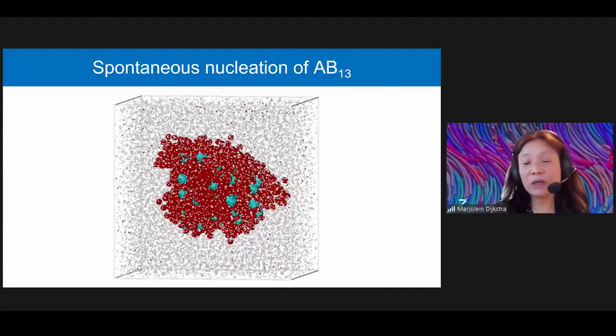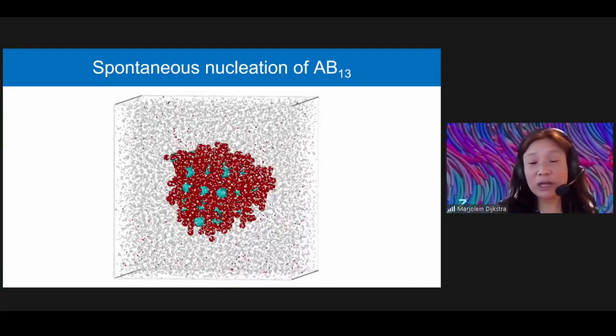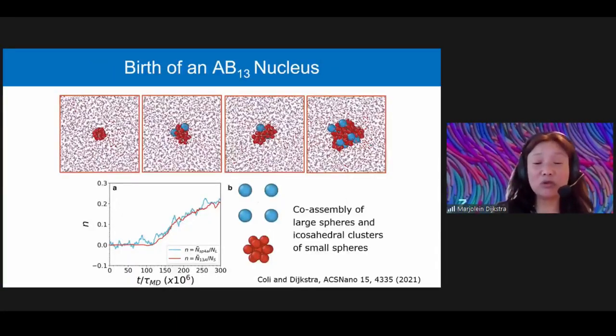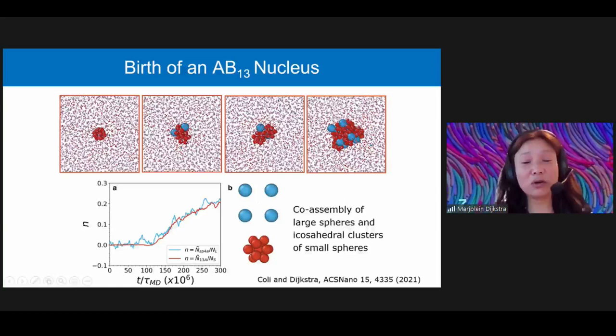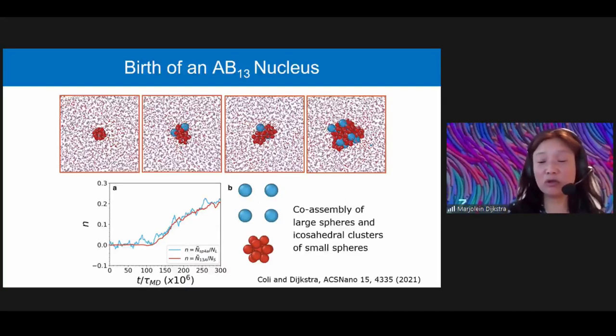And so that's where we run the simulation, and we indeed find the spontaneous nucleation of this AB13 crystal phase. So we can analyze the trajectory by using a cluster criterion, and we find that the birth of such a nucleus starts with an icosahedral cluster of 13 small spheres, then big spheres are attached to it, other icosahedral clusters are attached to it, and other big spheres. And if you plot just the number of big spheres that attach to the cluster and icosahedral clusters that attach to the cluster, we see really a co-assembly of large spheres and icosahedral clusters. That is very well described by classical nucleation theory.